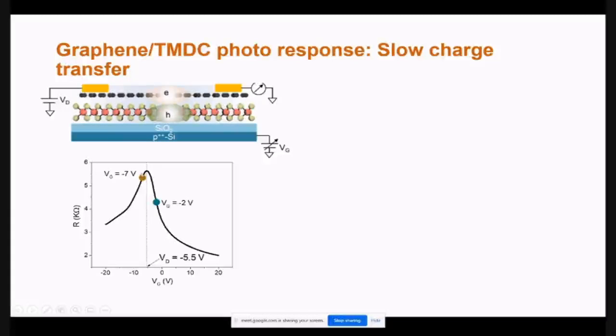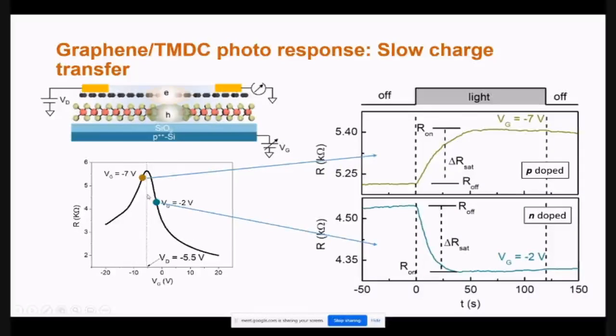But when you are at these 2 points, either electron doped on this side and hole doped on this side, and you shine light on it, then you see a very interesting behavior. You see the resistance of the graphene layer, I'm measuring resistance of graphene, changes when you shine light on it. When you are electron doped, which is here, the resistance decreases, meaning that the number of electrons has gone up. Whereas when you are on the hole side, shining light makes the resistance go up. That means the effective number of carriers has gone down. From this, it becomes clear that when you shine light, some electrons from the layer underneath have been transferred from the TMDC layer to the graphene layer. So this is what you call a photoresponse.